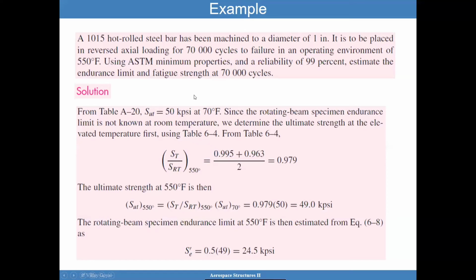So the ultimate strength of this material is 50 KSI at 70 F for a hot rolled steel bar, which has been machined. Since we're looking at a rotating beam specimen endurance limit and it is not known at room temperature, we'll have to estimate it. So we'll first determine the ultimate strength at the elevated temperature, and you can basically interpolate it to figure it out. And you get that this ratio is 0.979.